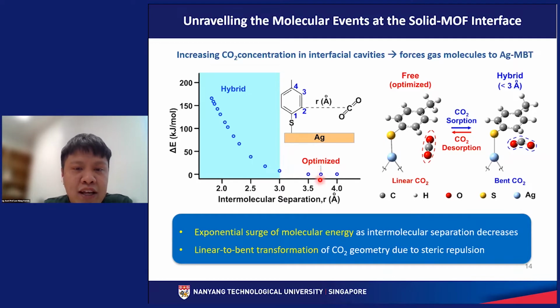In this case, without any interaction, we have an optimized intermolecular separation R of around 3.75 angstrom. From this position, we slowly let the carbon dioxide molecule approach our silver MBT surface. This will lead to an exponential increase in the energy of the molecular system. What is more interesting is that for the free state, whereby there is not much interaction between carbon dioxide and silver MBT, carbon dioxide is a linear molecule. Upon reducing the intermolecular separation, we see that the carbon dioxide adopts a bent configuration.